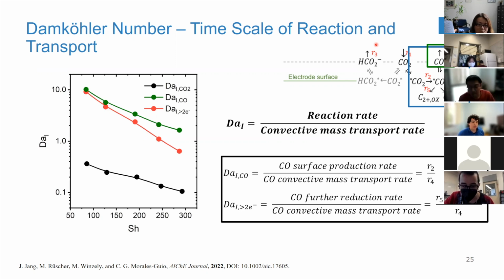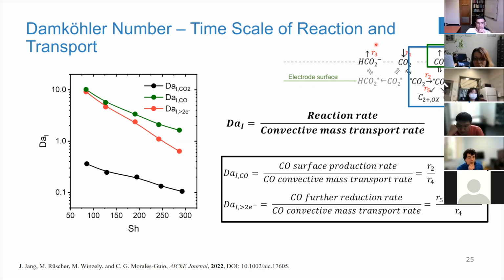Right. So CO2 and methane are very easy to do in the same system, because the products are gases and the gas products are the same. CO, CO2, and if you make methanol, you can also quantify the liquid. So we have also been using it for methane partial oxidation to methanol. Nitrogen reduction we haven't done yet, because we think you have a problem with the solubility of nitrogen. Fair. You will probably want to do it at high temperatures or high pressures at least. And then we do nitrate reduction, because it's easy to put nitrate into the solution, and then we make ammonia. So it's more a matter of what additional analytical tool you need to quantify products. But if it's things that you can quantify with the GC, we're doing it.